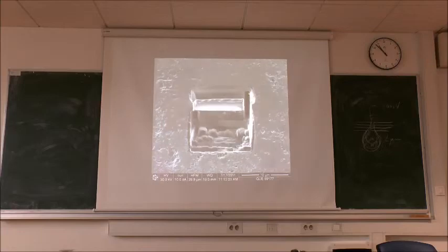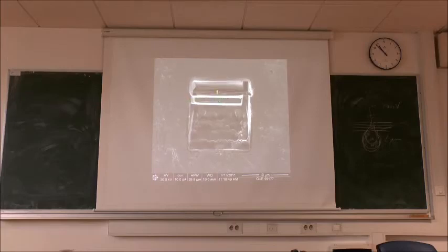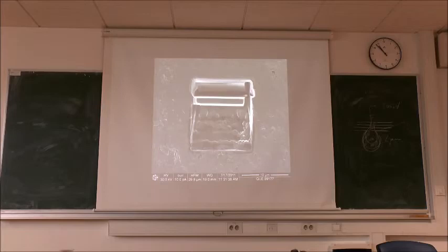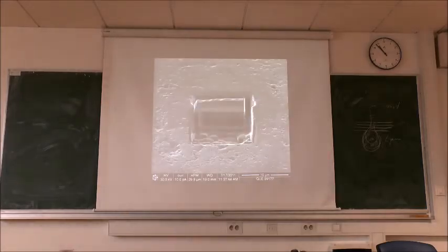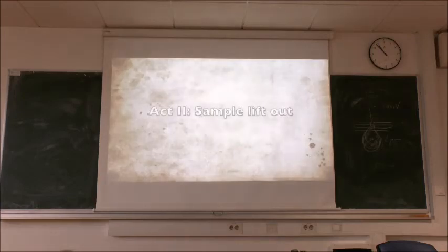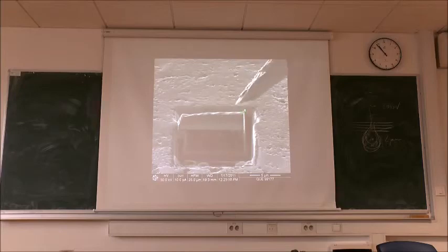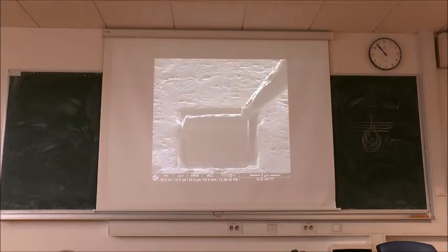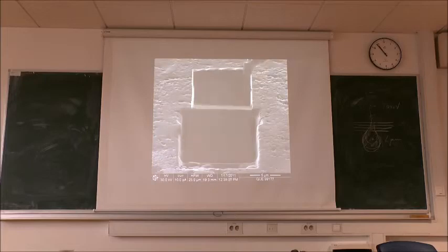You cut it here and there. You see, it's fixed just on this part. This is platinum. You can then use fine thinning, fine milling on this part and another part. You can thin it, but not down to the extreme, because this next part could resemble a Greek tragedy, because this is the most critical part. You see, the size of this is very small. This is micro-manipulated, and you should bring this micro-manipulator just a few tens or hundreds of nanometers, and you weld it here, you cut it there, and you get a lamella. Very easy, huh?